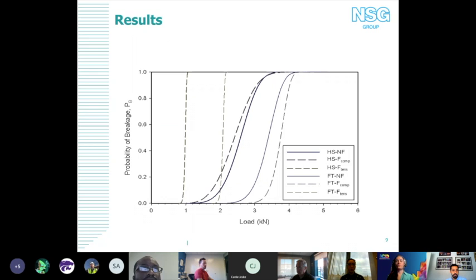And so if you look at, we'll say, mean failure load, what we started seeing was that fully tempered glass is actually performing at a load resistance less than that of heat strengthened, and heat strengthened was performing less than our annealed samples that we ended up testing later on. And so it's pretty significant whenever it comes to designing for load resistance.